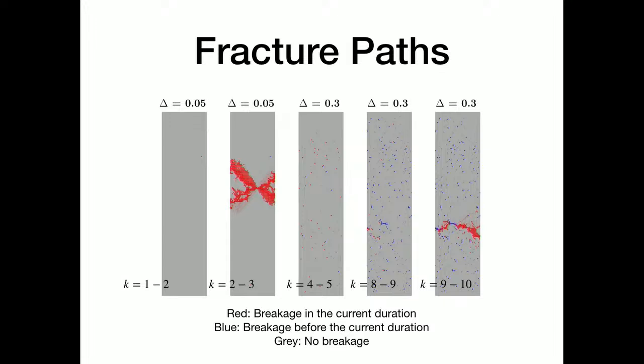So what we wanted to see was that for the small disorder, how does it look when we have a record which is just before final failure? We had only 3 records there. So 1 to 2, what is the red color is what broke in this duration. Blue is what was already broken, and gray is what did not break even now. So it's still intact. So you can see that there's very